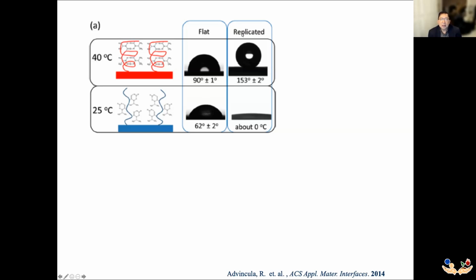But a surface that has a replicated lotus leaf pattern gives us a 153-degree angle or super hydrophobic effect, and about 0 degrees in terms of the wetting, indicating super wetting behavior.